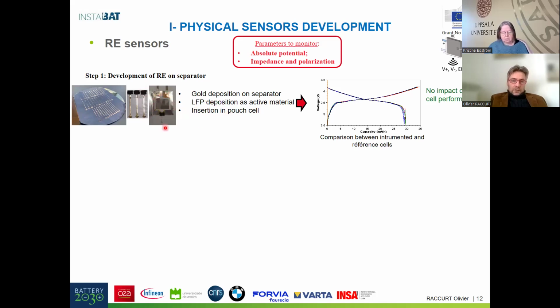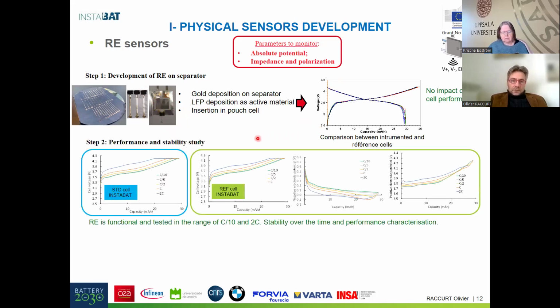You can see here an integration of this reference electrode into the pouch cell, and we checked that the presence of the reference electrode doesn't affect the electrochemical performance of the cell. And then we checked the behavior of this sensor at different C rates. And you can see here a comparison between the cell without reference electrode and the cell with reference electrode.